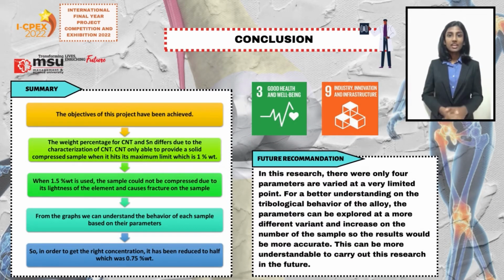Last but not least, in conclusion, the objectives of the project have been achieved. As the first objective, a sustainable porous titanium nickel shape memory alloy through the addition of binary elements such as carbon nanotube and tin with different weight percentages has been developed. The weight percentage for carbon nanotube is 0.5, 0.75 and 1 weight percentage, therefore for tin 0.5, 1 and 1.5 weight percentage. There were different variables being used to obtain these results, which are speed and the load.